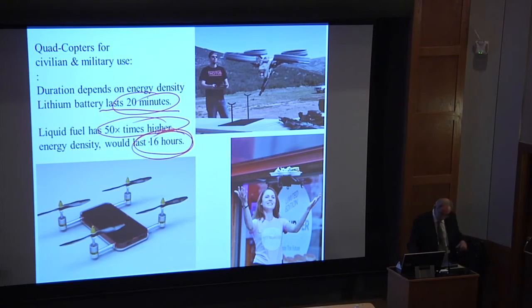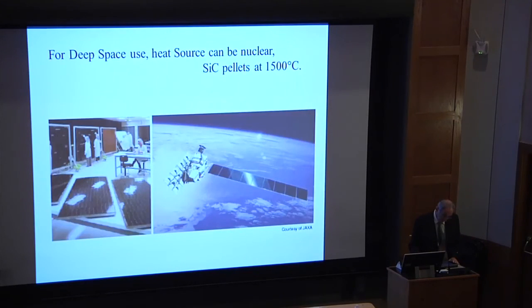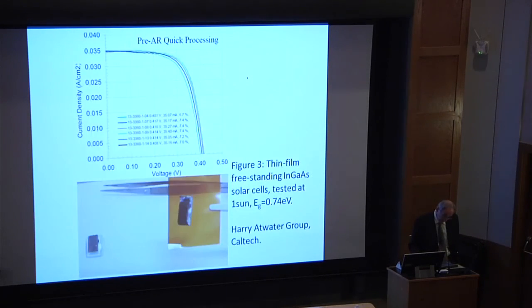In this application, it would just be the size of a business card. You'd be producing about 100 watts in something the size of a business card. It's a little tiny thing. And then I mentioned the space application, which we already have some colleagues at Berkeley working on. Interestingly, if you have silicon carbide pellets embedded with plutonium, don't do this at home, they'll just self-heat to 1500 centigrade. And that would be suitable. It's amazingly stable. It will be stable in vacuum at 1500 centigrade for long periods. So that's kind of amazing.